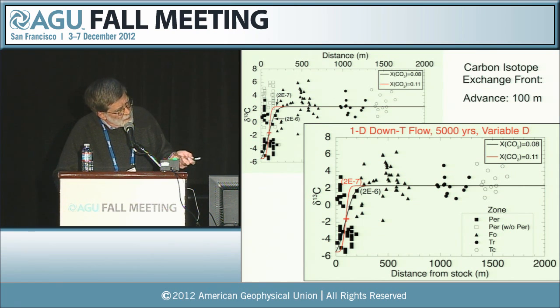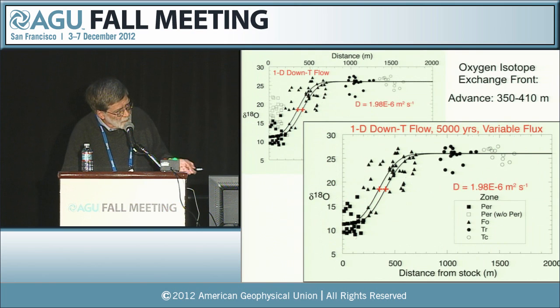Now, the 1D models can't show you that two-dimensional structure. Two-dimensional models have been made by folks like Gerdes, Baumgartner and Person a few years ago. And what they did was simulate, I can actually go back to the oxygen front here. Their conclusion was that, yes, indeed, there's a very significant vertical permeability heterogeneity that has to be in the system to produce this kind of dispersion, confirming what we said as well.